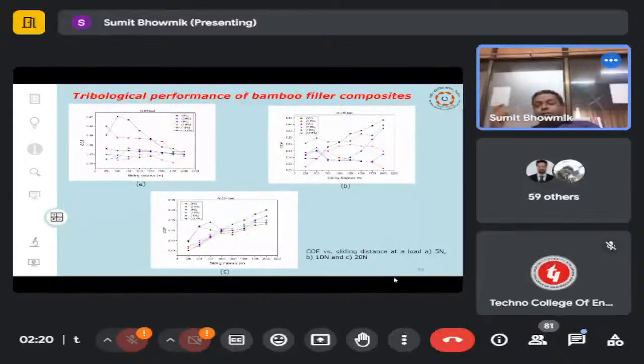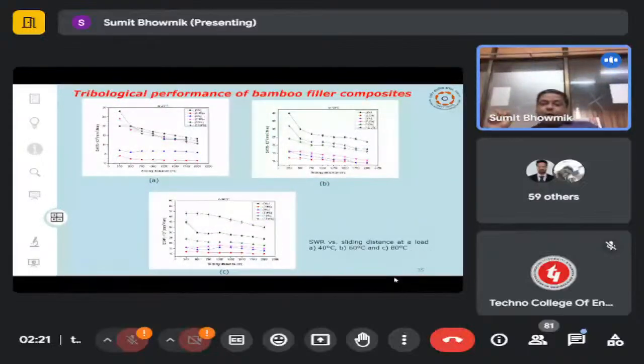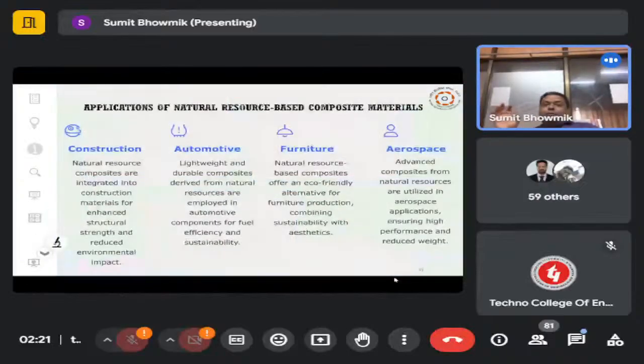So in general, with the variation of filler content, the load has been varied from 5 Newton, 10 Newton, to 20 Newton. Also the sliding distance has been varied from 1000 meter to 3000 meter of the component to get the proper idea. Also the temperature has been varied from 40 degree, 60 degree and 80-degree temperature to get the proper result.